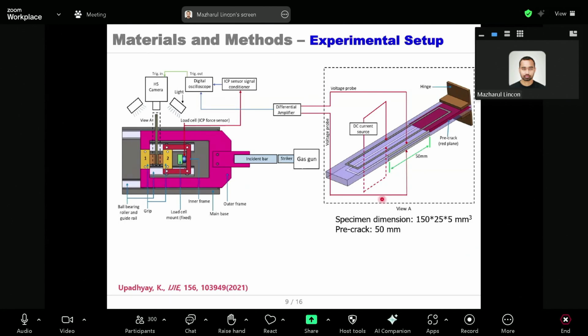Rectangular silver paint is applied on the top and bottom surfaces of the specimen, and using this silver paint, current passes through the thickness direction. On the right plane of the specimen, two silver paint strips are used to measure the voltage during crack initiation and propagation of this DCB specimen.